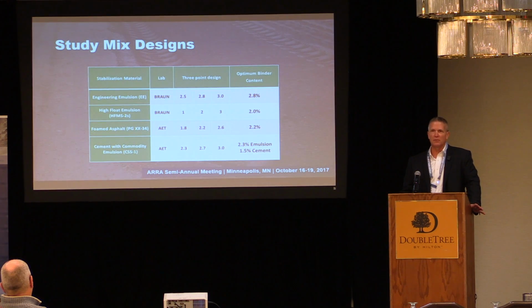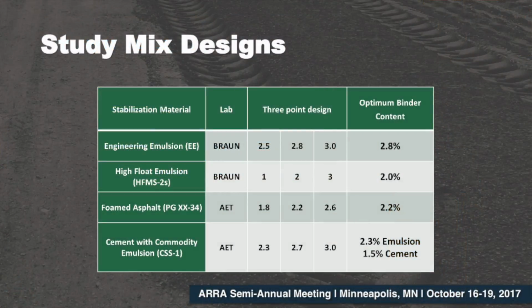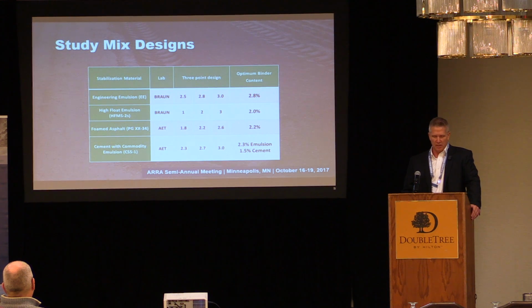So really, to set up these designs, we wanted to look at the most commonly used stabilization materials in Minnesota, and those are engineered emulsion, high float emulsion, foamed asphalt, and cement with commodity emulsion. Braun Intertech did the designs for the engineered emulsion and the high float emulsion, and AET did the design for the foamed asphalt and the cement with the commodity emulsion.